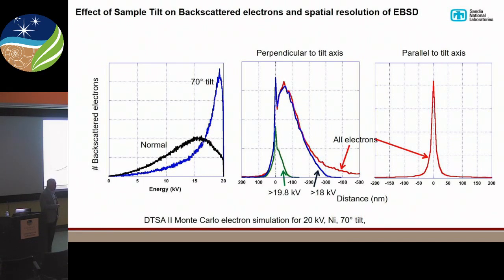In terms of resolution, what's happening? Well, here's our beam impact point. Remember, we don't care about all the electrons. We just want to know where the ones that have lost very little energy come from in our sample, and that's very near our beam impact point. So if you look here, here's the impact point. The green curve is for the electrons that have only lost about 200 eV, and we can see our resolution now is sub tens of nanometers.